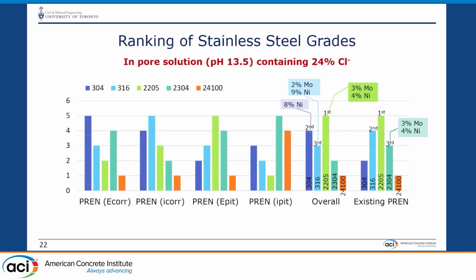When you look at that PREN formula, we developed it based on E-corr, I-corr, E-pit, and I-pit, because, like I said, the stainless steel alloy compositions are very sensitive to either of them. So it was important to develop 4 different types. The existing one has 2 different types, for duplex stainless steel and austenitic stainless steel, so it's not impossible to have more than one PREN formula.